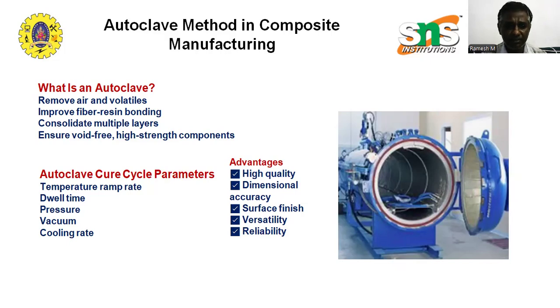An autoclave is a pressure vessel designed to process composite parts by subjecting them to elevated pressures of about 6 to 10 bar and temperatures of 120 to 180 degrees Celsius under controlled conditions. It allows the simultaneous application of heat and pressure to remove air and volatiles, to improve the fiber resin bonding, to consolidate multiple layers, and to ensure void free, high strength components. So the working pressure is 6 to 10 bar, as I said, and the temperature is 120 to 180 degrees Celsius.